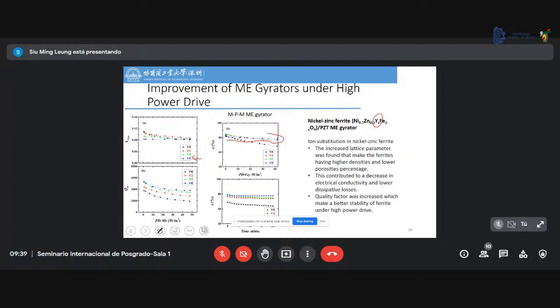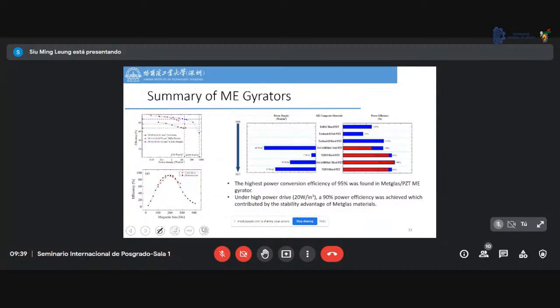We can find that the blue one is the power efficiency when we drive in the high power region; the power efficiency can remain about 80%. But for the original one, if we drive at 40 watts per inch power density, the power efficiency will be reduced to about 60%. Okay. So there's some other improvement.